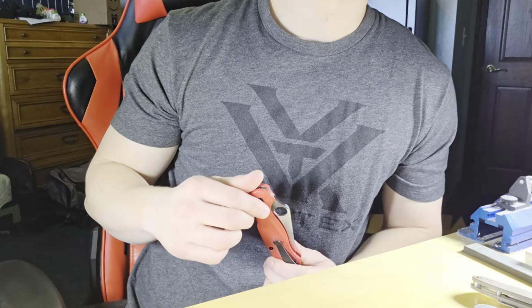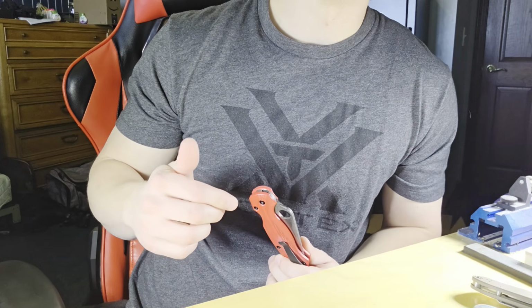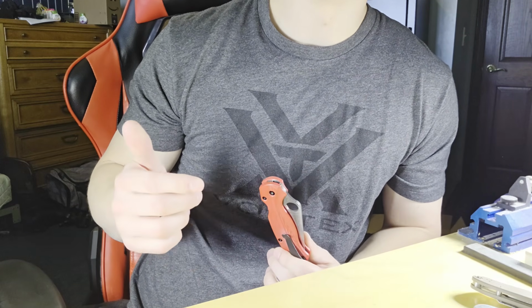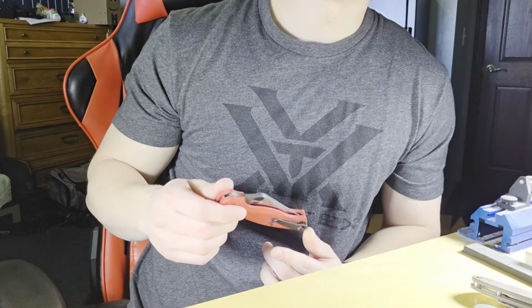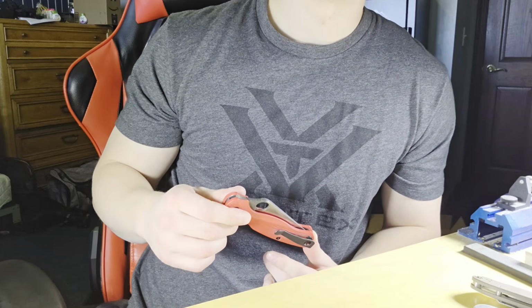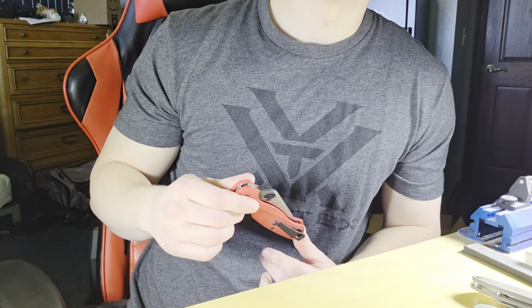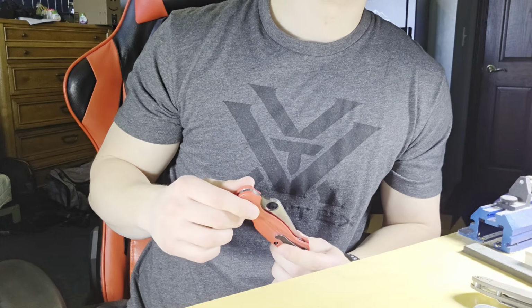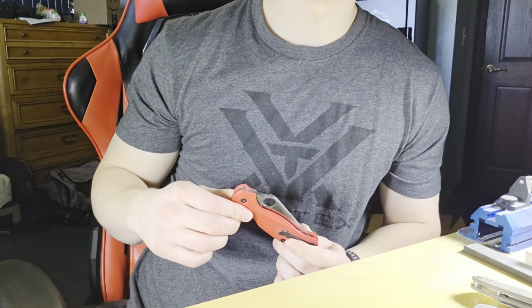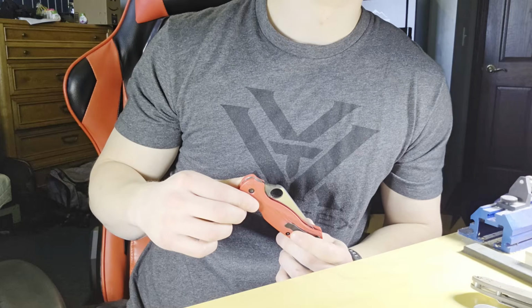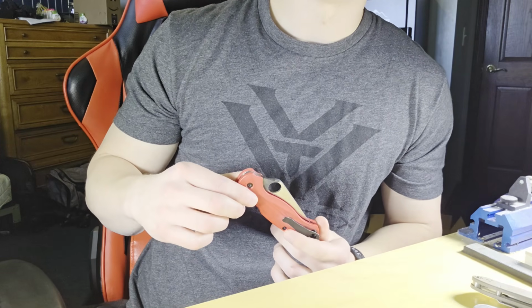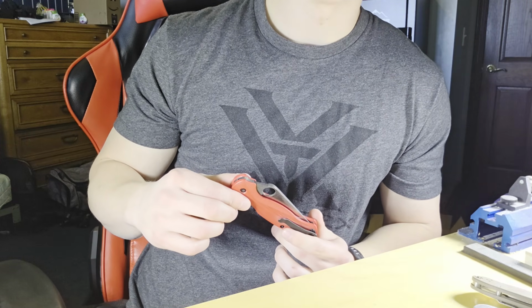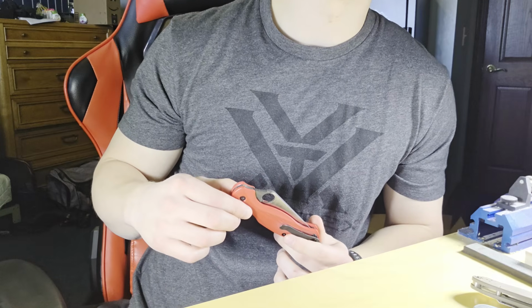Now, we know that fine grain structure is preferable for better toughness, edge stability, sharpening, and other qualities. The carbides actually help in that too. Carbides help pin grain boundaries so they can't grow. So if too much carbide gets dissolved into the steel, excessive grain growth can occur, which leads to inferior properties. It's going to have lower toughness. It's not going to sharpen nearly as well. The edge isn't going to come up as crisp.